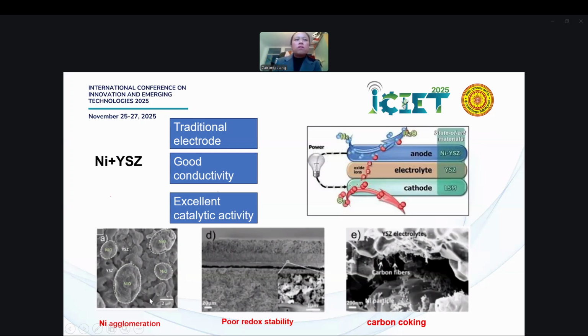The first is the nickel agglomeration. Because all the cells are working at quite high temperature, like 600 degrees or 800 degrees, the nickel agglomerates over time. I mean, they lose their ability or capacity. The second problem we have is the poor redox stability, and you can see a big gap between the cells. This is the nickel's problem.